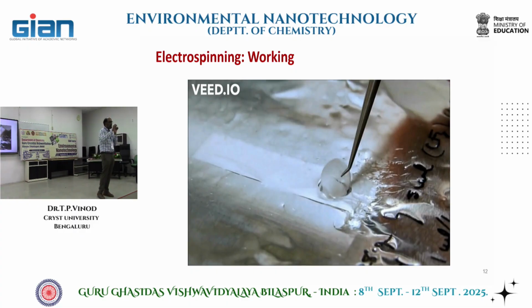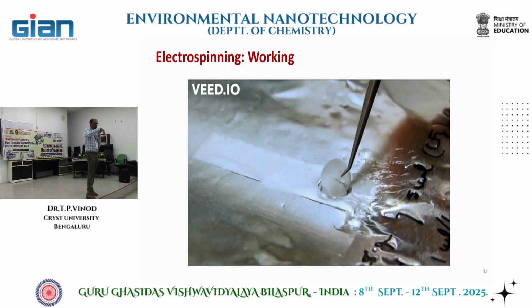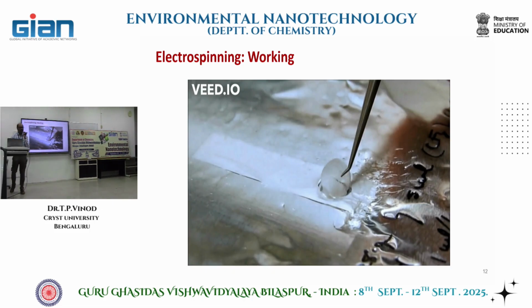Yeah, so if you have a stationary collector like this, the deposition is not happening uniformly everywhere. So you want a very uniform coating and a continuous film. For practical application, it's always better to have a film of uniform thickness. So that's why you keep on rotating it. And then that rotation speed also decides the quality of your film. That's another parameter we need to customize, we need to optimize. Okay. So yeah, I was distracting you from the video.